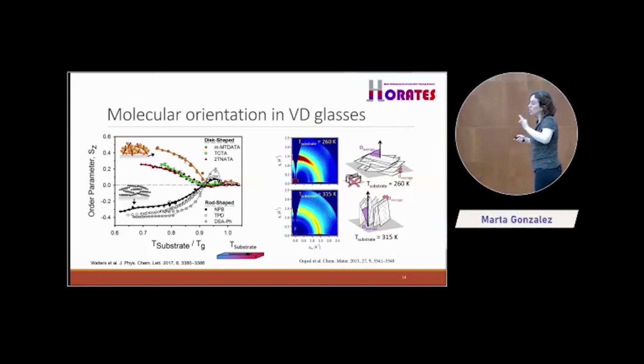Related to this, although it's not exactly the same, but it's related, of course, is not only that the molecules tend to be flat, but also you start to have some correlation distances. If they are more or less flat, you see a packing, okay, that shows in, these are GIWAXS measurements, okay? You see that here, this is not completely random, because if the molecules tend to be flat, you also start to see a repeated distance here in the packing of the molecules, okay? And this gives you this maximum here in the profile.